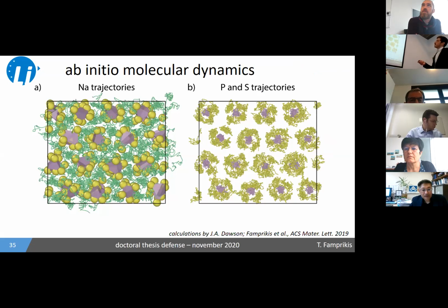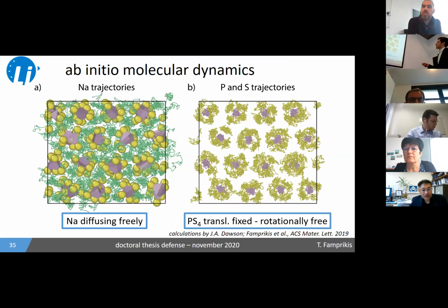Basically what we're doing here is just tracing the trajectories of the simulation that you just saw. On the left, we have the sodium moving around in green, again diffusing very, very freely with no distinct hops between distinct lattice sites. And on the right, you can see the phosphorus and the sulfur trajectories. You can notice that the PS4 as a unit stays translationally fixed, but the sulfur is very free to rotate around the central phosphorus, doing basically free rotations around the phosphorus.